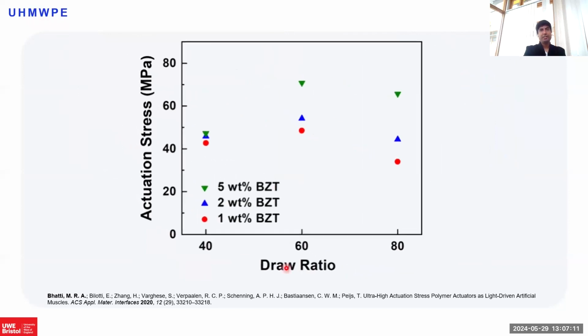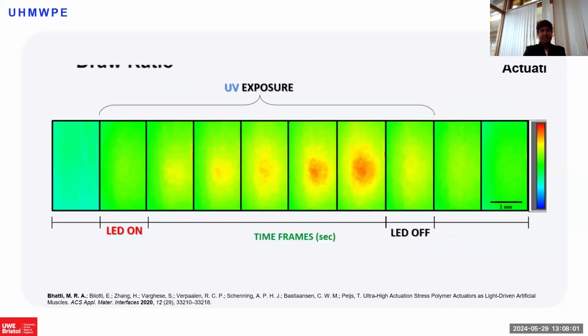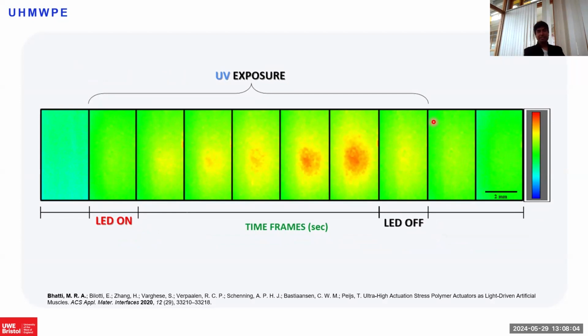And we were aiming to get a higher actuation stress, which was actually the case, and we successfully got a higher actuation stress by just increasing the draw ratio, getting the thickness of the film to the lower side. But as we were anticipating that increasing the draw ratio would increase the actuation stress, to our surprise, we got a plateau. We did not get a regular steep curve. We got an optimum value. At a draw ratio of 60, we get the maximum possible actuation stress with these films. And as we increase the draw ratio, the actuation stress decreased, which was a surprise for us at that moment. And it's important to mention over here that